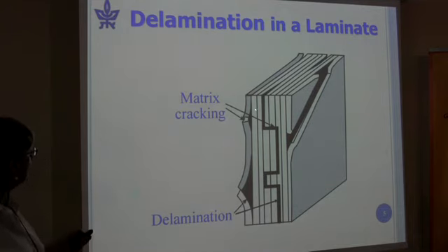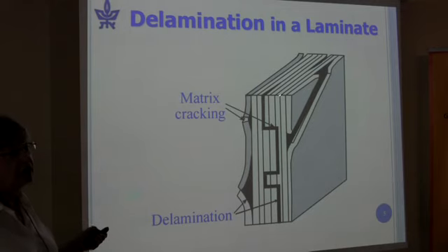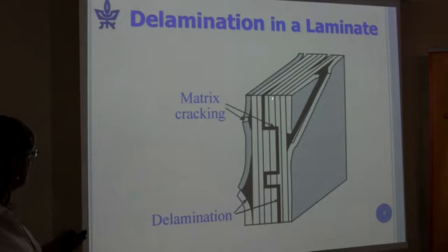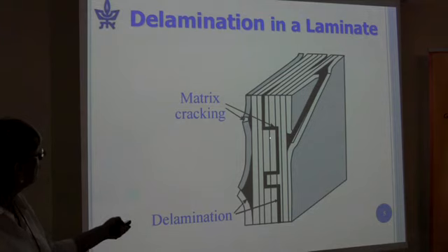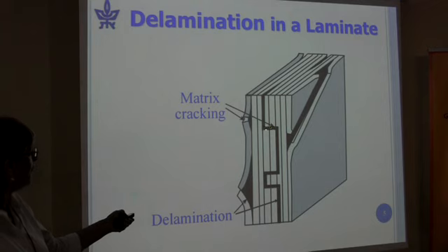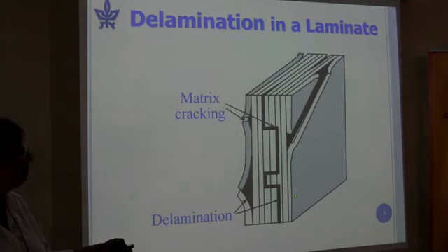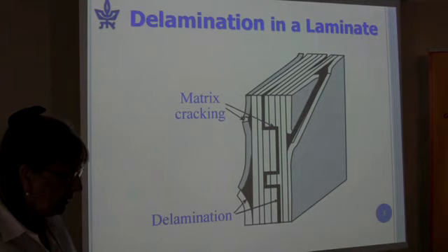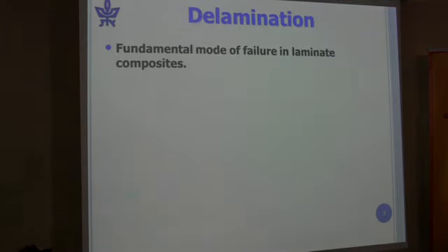And then typically what happens is we have different failure modes. The 2 most prevalent failure modes in laminate composites are matrix cracking. That is, the fibers here, let's say, are not in the 0 degree direction, because that would be very strong, and we get cracking through the matrix, through the epoxy, for example. Or another mode of failure, and that's what we're going to speak about, is delamination. We get a separation between the various layers, and that's a very prevalent mode of failure.